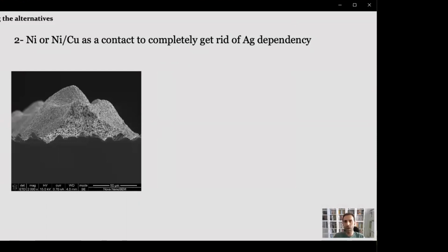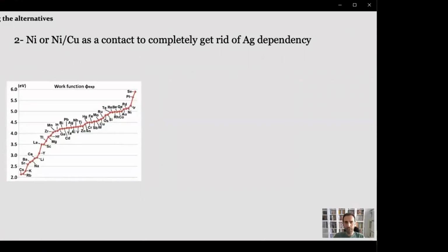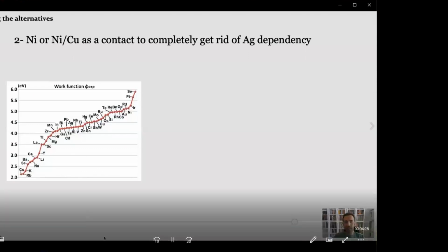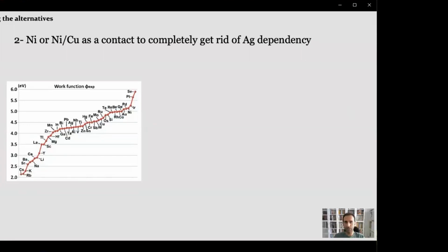Ideally, metals would form ohmic contacts if their work functions align with the conduction or valence bands of semiconductors. In practice, however, when a semiconductor forms a contact with a metal, a potential barrier called the Schottky barrier emerges as a result of misalignment between the work function of the metal and the electron affinity of the semiconductor. This graph shows the metal work functions for different metals. Considering silicon has 4.08 eV electron affinity, copper and nickel have a higher metal work function. This will result in a Schottky barrier height that causes the contact resistivity.